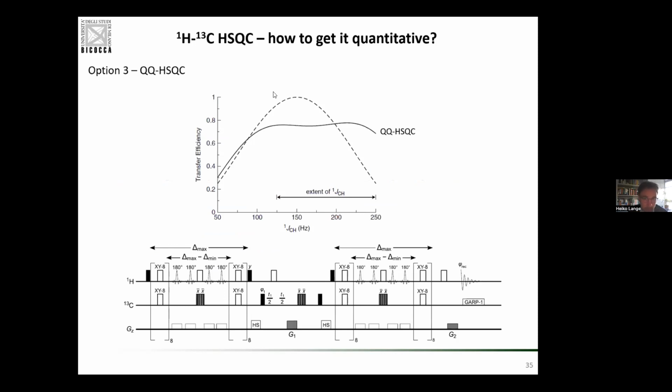But that's a nice thing, because I basically get rid of all the ketones, all the carbons that I'm not really interested in, because they contain less interesting information in a first hit, let's say. So I only see HC, H2C, or H3C groups, depending on the coupling constants, which in turn depend on the structural environment of the specific carbon that I'm looking at, with its protons